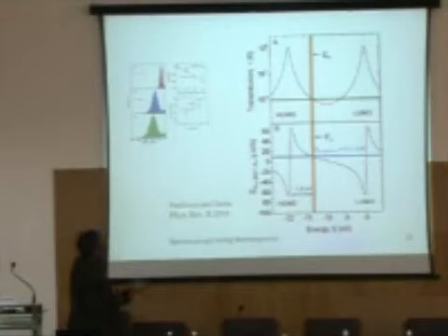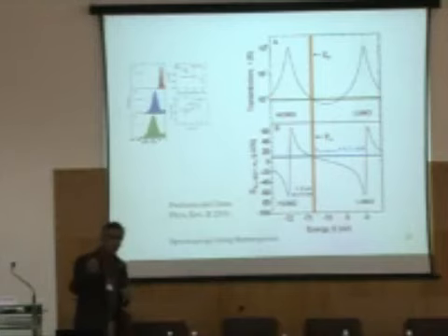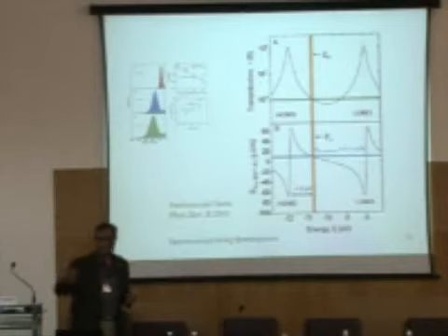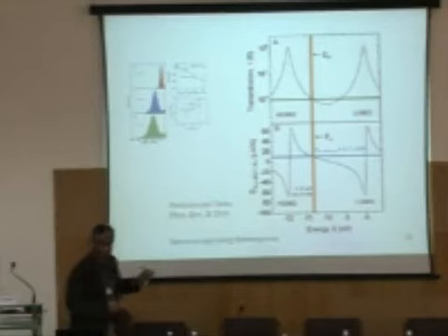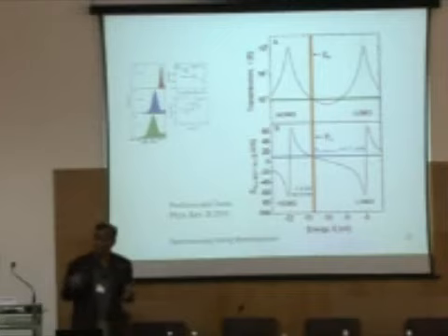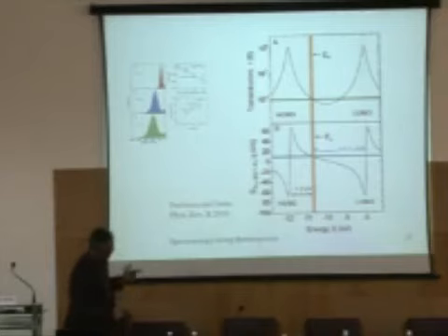As you tune, as the Fermi energy hits this, there is a resonance transfer. Now you can use that and compute the thermopower, pretty straightforward. Essentially, once you have a temperature gradient, there's a formula. You can calculate thermopower as a function of the chemical potential, and you plot it. What you find, interestingly, is that now you know your measurement, you put it in, so you can locate where the HOMO or LUMO is vis-a-vis the metal Fermi energy. So it's a nice experiment which tells us how I can use this nano thermoelectricity for doing spectroscopic measurements of molecule levels. May not be the most efficient, but that's a...